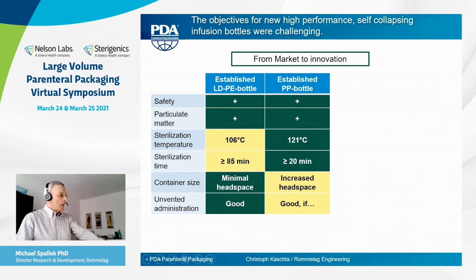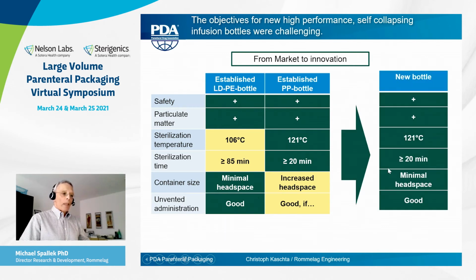However, you need to increase the container size to have an administration procedure, an application without venting the container. That's fine for the LDPE bottle because it's soft. It's not so good for the PP bottle because this is much more rigid. But from the microbiology point of view, you want to avoid having a vented container. That's why we put up the development task having a high performance self-collapsing container. So the new bottle should fulfill all these requirements quite nicely.